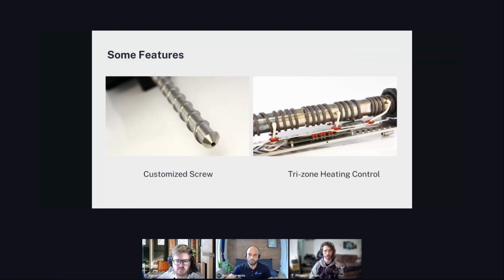The top section receives cold pellets and generates more heat to melt them. Then, the middle zone stabilizes the polymer at a precise temperature. Finally, the nozzle heater ensures an even flow.